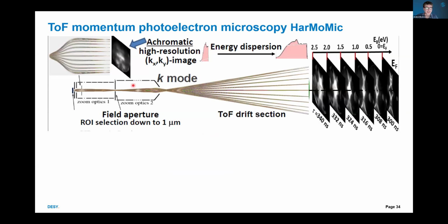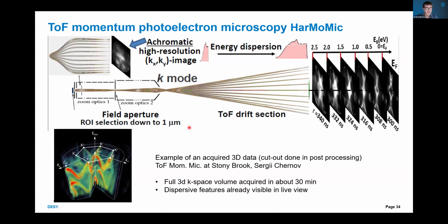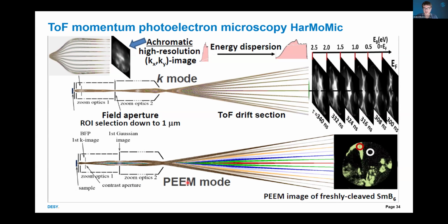One more bright idea is the momentum microscope, and it's based on the fact that every electrostatic lens has an angular image in its backfocal plane. So if you then afterwards do the energy dispersion of the photoelectrons and image not the Gaussian plane but the backfocal plane, you receive the 3D Kx, Ky, and energy image cube at your detector. And this is how the bands look. And the experiment is pretty fast. You can acquire the full 3D k-space in about 30 minutes. Also this microscope can work in the PEEM mode, but the resolution is not as good as the momentum resolution.